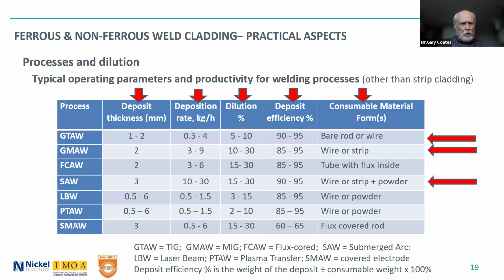I'll leave flux core for a moment, but the subarc is a common way of doing weld overlays. It can be semi-automated. There you do get high deposition rates, but you also get high dilution rates. But you get also a thicker weld deposit, which often is an advantage. So sub-arc welding is often used for weld overlays. There's also laser and plasma. I'll talk about those very shortly.